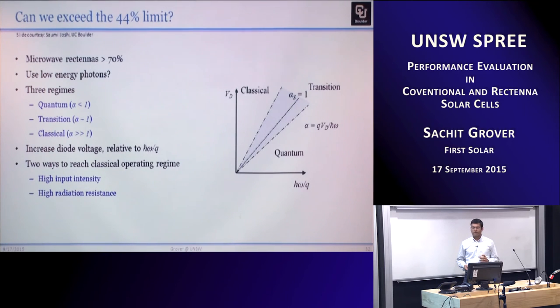So can we exceed the 44% limit? Well, the short answer is yes. Long answer is yes, but it's difficult. And the reason it's difficult is because we have to break away from this quantum regime where we are in a one photon process and get into a classical regime where the AC signal that is applied across the rectenna is large enough that there are multi-photon processes happening in that regime. And again, you can find parallels to that with the semiconductor-based solar cell field, where if you have a multi-photon process, you can break the Shockley-Queisser limit.